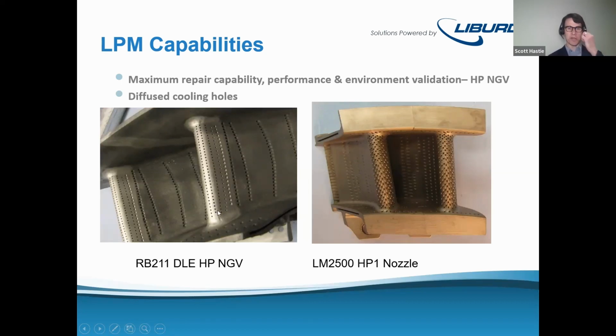One of the cool things here is that we're able to return the size back down to nominal position. What we see during operation is those holes will tend to get slightly larger, and as they get larger, you're going to see some degradation. It will redirect cooling flow to that leading edge as opposed to somewhere else. So that's an important part of why we do the repairs, less so on maybe the RB211 that doesn't have an airflow requirement, but the LM2500 does, and that allows us to meet the criteria to go back in the engine.